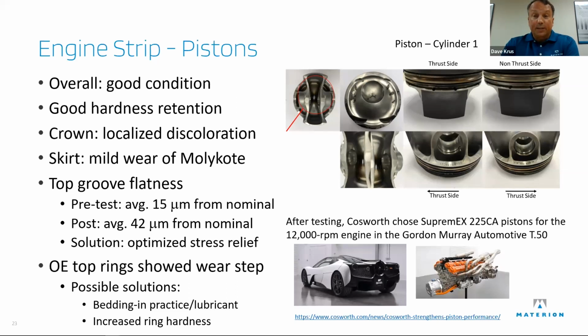The one thing we noticed was that the cast iron OE rings actually wore against the Supremex. So that was a little bit of a worry. The thing is, though, we've never seen them wear against tool steel rings, chrome steel rings, DLC coated or chrome nitrided. There's no ring wear. The other thing, if you have to use a cast iron ring, maybe a little bit better bedding in practice, a tungsten disulfide coating on it, or a little bit more red grease might have done it. So we weren't expecting that. It's just a note that you need a hard ring to run against that surface.